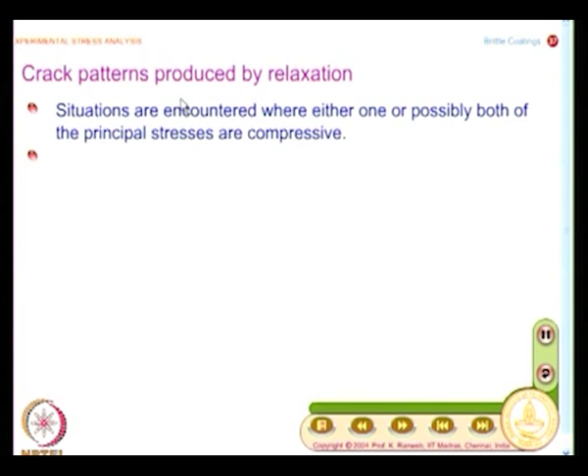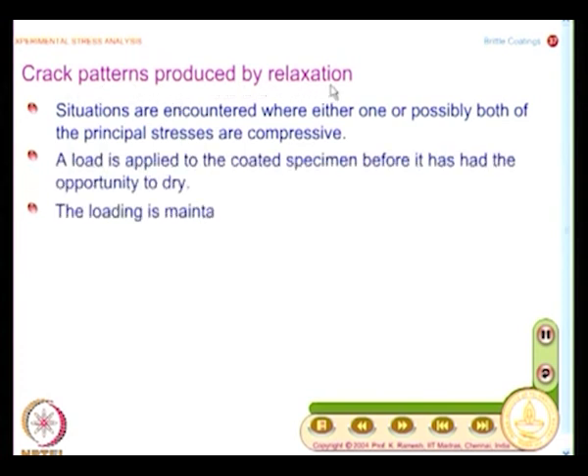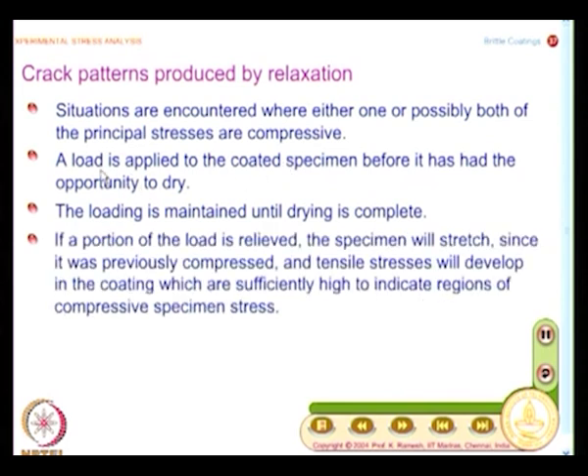And what do I do for compressive stresses? You apply the coating differently. What you do is, when I go for compressive stresses, which is known as crack patterns produced by relaxation, you load the specimen first. A load is applied to the coated specimen before it has had the opportunity to dry. The loading is maintained until drying is complete. So, what will happen when you release the load, whatever the stresses that were compressive, they will behave like tension. So, you will have cracks form. So, you have crack formation very similar to what you saw in direct loading. Then you can mark those, but these are very difficult experimentation.